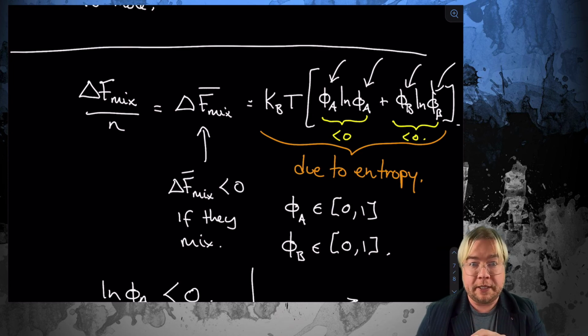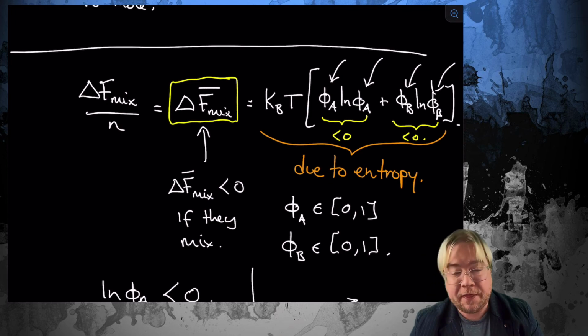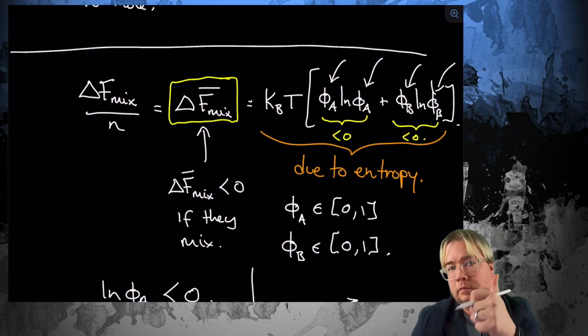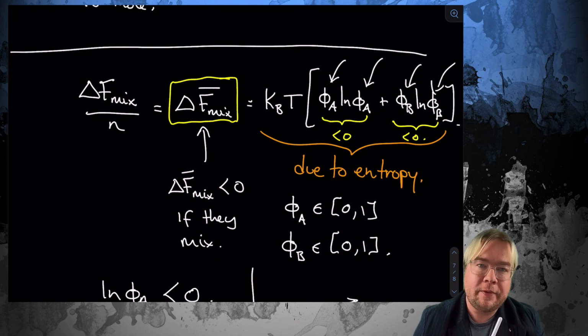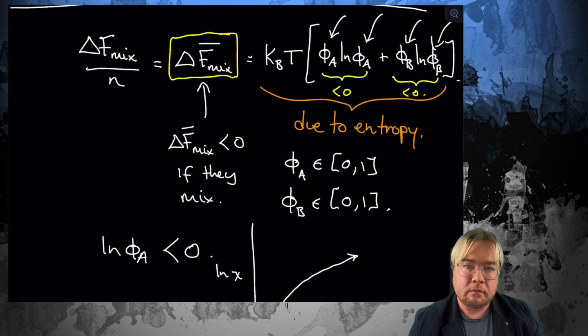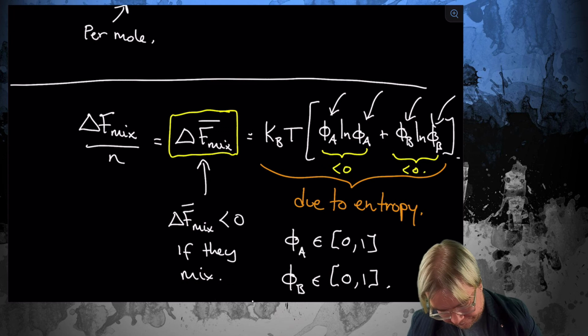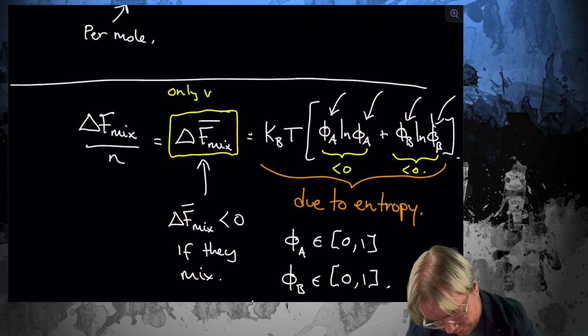So at least according to entropy, if there's no preferential interactions in the system, the free energy of mixing is going to be due only to entropy. Well, according to that, then things will always mix together. So that's fantastic. That's exactly what we expected. Okay, so we have a bit of a problem, though. Have I said anything about polymers yet? Well, other than introducing this video, no. Nothing that I've done so far really depends on polymers. So this expression, as I've given it here, is only valid for small molecules.